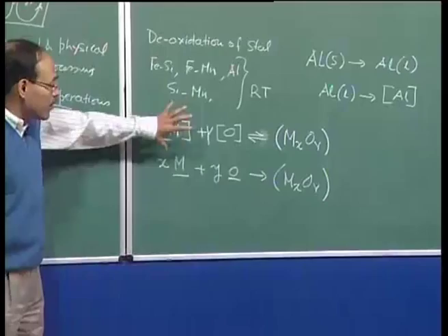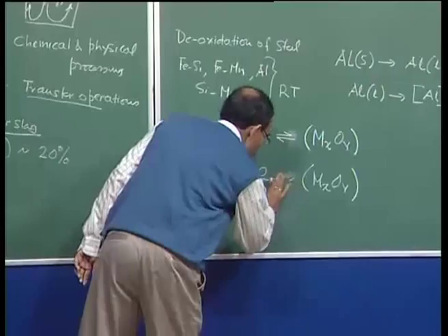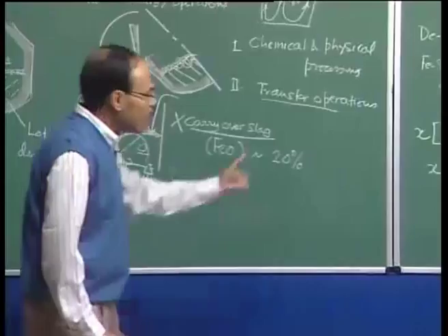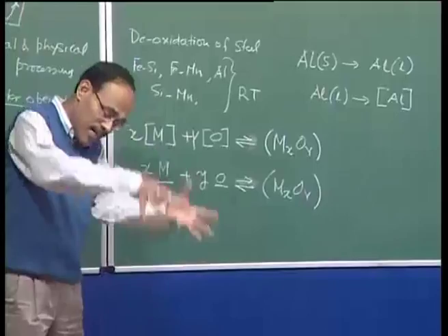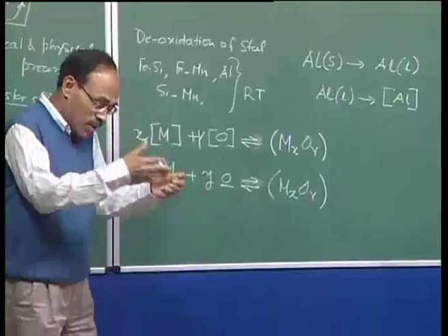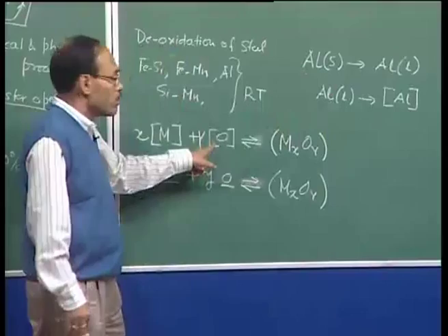It is about to reach or operating close to equilibrium itself. And this deoxidation equilibria we are going to study in great detail. But before this reaction can take place, if it is aluminum, then the solid aluminum I have added has to melt, the solid aluminum has to dissolve, and then there can be reaction between dissolved aluminum and dissolved oxygen.